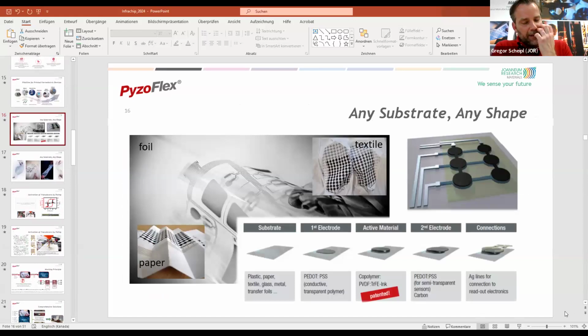So when you see it's like a standard vertical printing where we have this electrode, the active material, the electrode, and finally the connection lines, which altogether is about 15 to 20 microns at max. And of course, if needed, we print an encapsulation on top, where only the contacts of the silver to the next, like a cream flex or whatsoever, are left free. So we can fully shield it.